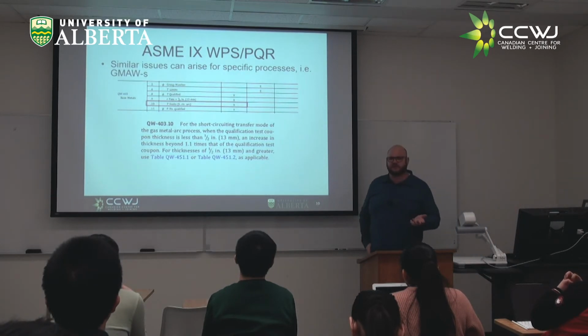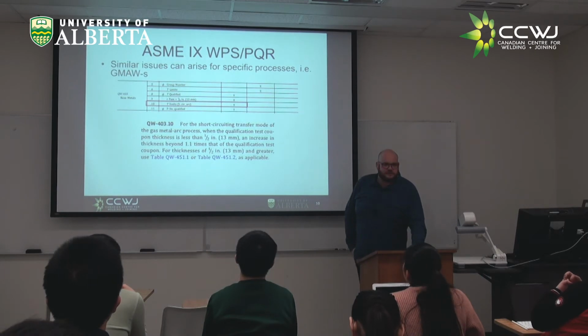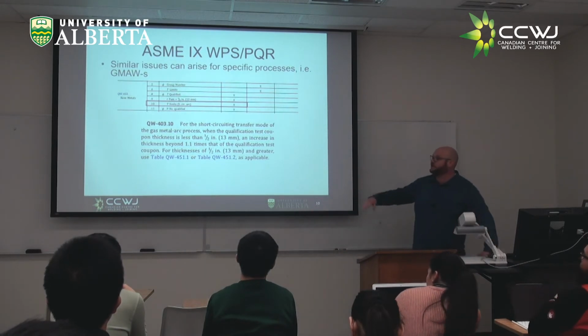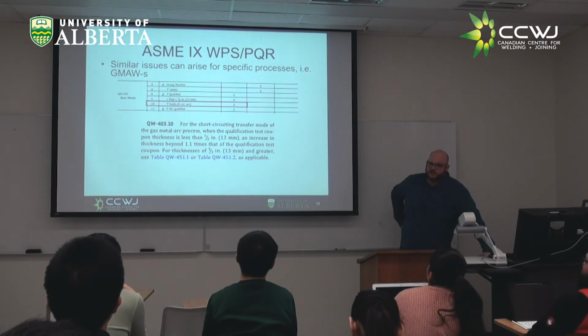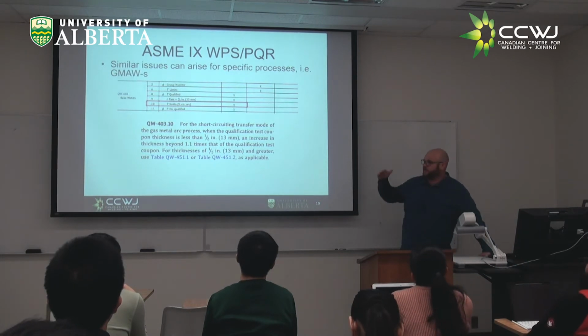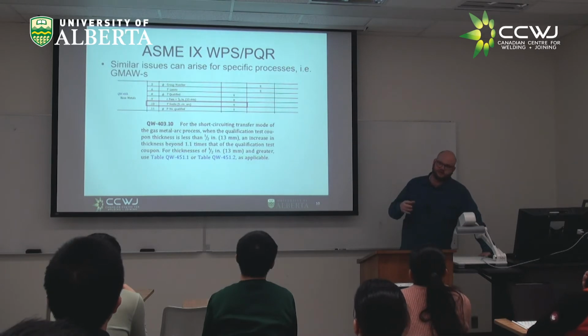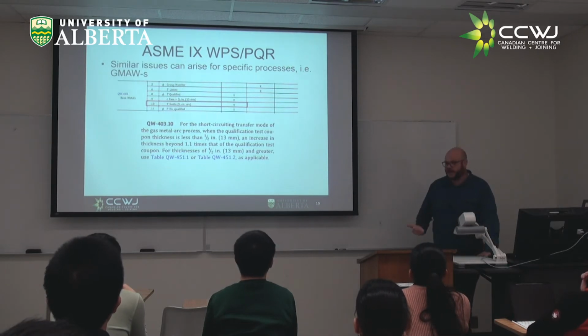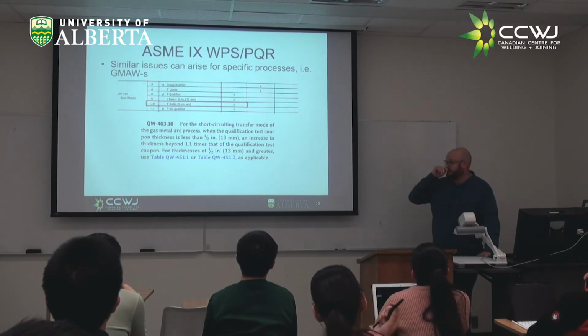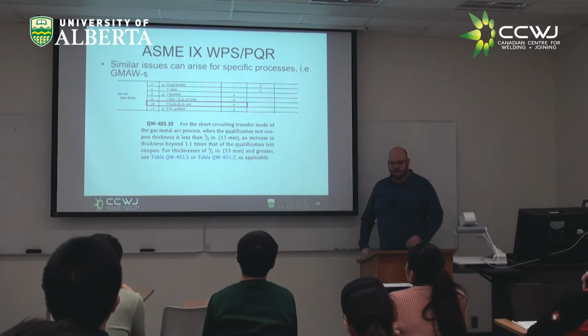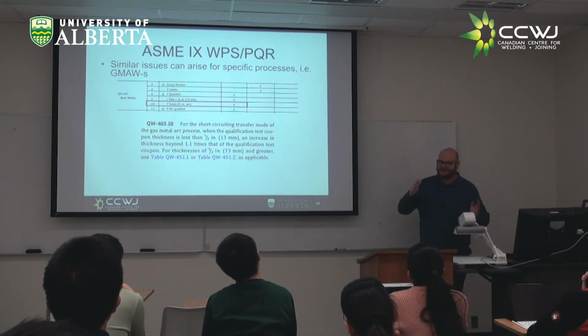Have you guys gone through short circuiting transfer modes for a MIG? Everyone knows it's a high deposition, low heat input process. The problem is they found in industry, the very hard way, that because of the low heat input, if you qualify on a thin coupon and then go to a thicker coupon, it's more prone to severe weld defects: sidewall lack of fusion, unacceptable root profiles, cold laps, just rejectable indications. So much so that they wrote it into the code that if you qualify on something that isn't sufficient to get that cooling rate to steal the heat, then you're limited to 1.1 times the thickness.